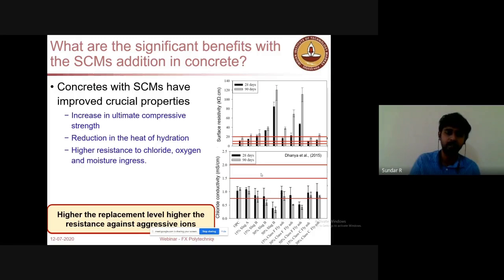When you use SCM-based concrete, you won't have some of those issues. Then there is higher resistance to chloride, oxygen and moisture. This is the most important point regarding durability. Some of the critical elements on earth which could be harmful for concrete are chlorides, oxygen, CO2, and moisture. If you have a concrete with a lot of pores which could absorb these compounds or elements, that could eventually lead to issues with respect to durability. I will explain later what durability issues happen.